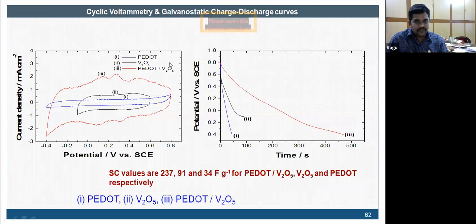The other system also here, the material combination, as I mentioned: the polymer alone, metal oxide alone, and the combination of these two things. Similarly here, PEDOT and V2O5, when they are alone, their activity is minimum. The moment they combine together, you could see that there is an enhancement in the current, that means obviously higher capacitance, and you can see clearly here.